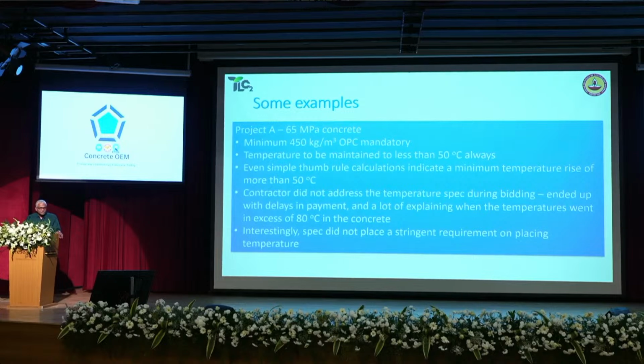And the spec also said that the temperature needs to be maintained at less than 50 degrees Celsius all the time. Inside the concrete, the temperature should always be 50 degrees or less. Now, any rough calculation you do will show you that 450 kilograms of cement will lead to a temperature rise of more than 50 degrees Celsius. Whatever temperature you cast your concrete at, you will get a rise of more than 50 degrees Celsius. So that means if you have to ascertain your concrete remains below 50 degrees, you have to do concreting at 0 or negative temperatures. Who's heard of these kinds of things? Unless, of course, you are planning to use cooling pipes inside your structure that will ensure that the concrete will remain cool, less than 50 degrees, all the time.